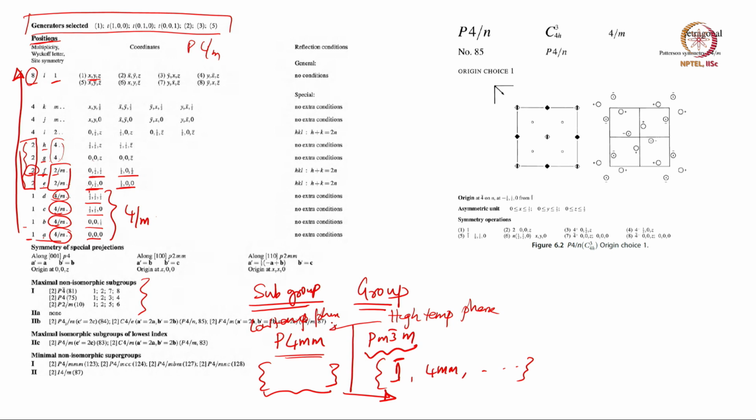Typically in phase transitions, not always, but what are called second order phase transitions, a material, when it is transforming from a high symmetry phase to a low symmetry phase, goes from a certain space group to its subgroup, right. So the subgroup has fewer symmetry elements, and you have to just kill some of the symmetry elements to undergo that phase transition. So the group subgroup relations become important in the context of phase transitions.